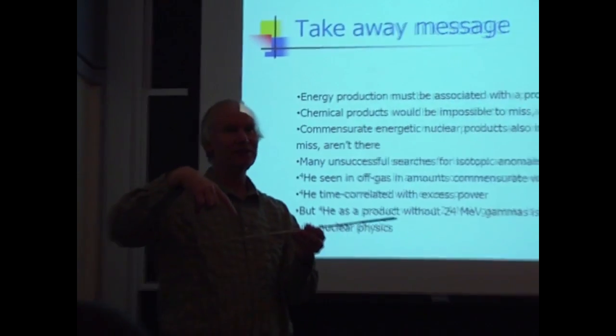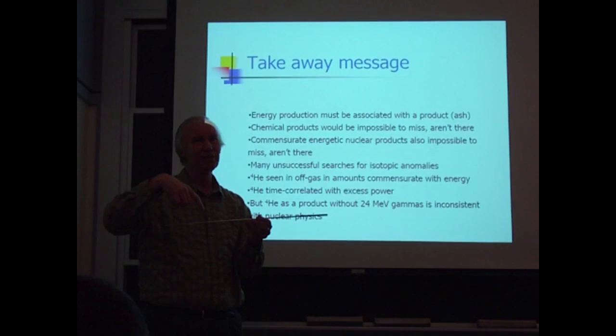Mitchell actually clarified the big issue. Back in the early 90s, I was thinking along similar lines to Mitchell with respect to the optimal operating point. So the argument was there were reports of neutrons, reports of tritium, reports of excess heat. Let me imagine there being a line. For the Fleischmann and Pons geometry in lithium deuteroxide, the question is, what's the electrochemical current density associated with each? So for example, neutron production was reported between 10 and 30 milliamps per square centimeter. Tritium production was reported around 70 milliamps per square centimeter. And excess heat production seemed to me 200, 300, 500 milliamps per square centimeter.